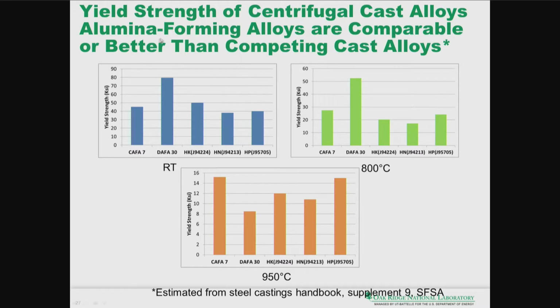So in terms of the strength, here's the data showing the strength of these alloys at 3 different temperatures. As you can see, the DAFA 30 is aimed at being a very, very high strength alloy, and it's at least about double the yield strength of the other austenitic stainless steels that we show here. CAFA 7 does well. And it's at least comparable, maybe slightly lower at room temperature than HK, but definitely better than the HN and the HP.